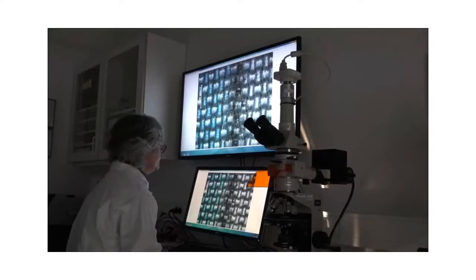To look more closely at the result of the different treatments, the test pieces were studied using a light microscope. Using the microscope, it is easy to see if the ink had bled beyond the pencil contours. The results show that cyclododecane in 1 or 2 layers only has very small colour bleeds, and that those which included paralloid B72 show no bleeding at all. But if the paralloid is outside of the ink, it's not possible to remove it. It had been thought that it would be easy to lift away once the cyclododecane had evaporated.